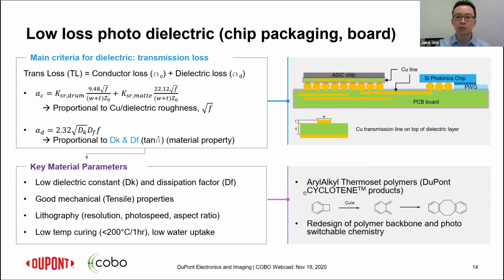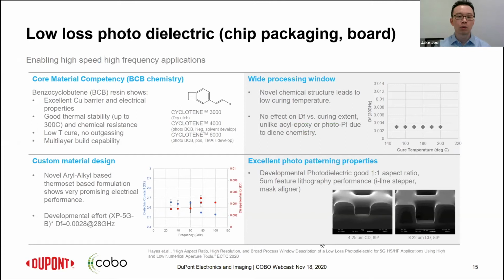As I mentioned before, we have basics of cyclotene types of material, PCB material. We have been working on revising those materials from the APT group in electronic imaging, to see if some change in the polymer backbone, as well as the photo package, will be able to deliver the properties we were looking for. So we were able to develop customized material based on the fundamental understanding we had with BCB, and based on that, we were able to get the Df value at 28 gigahertz less than 0.0028, as well as dielectric constant less than 2.7.